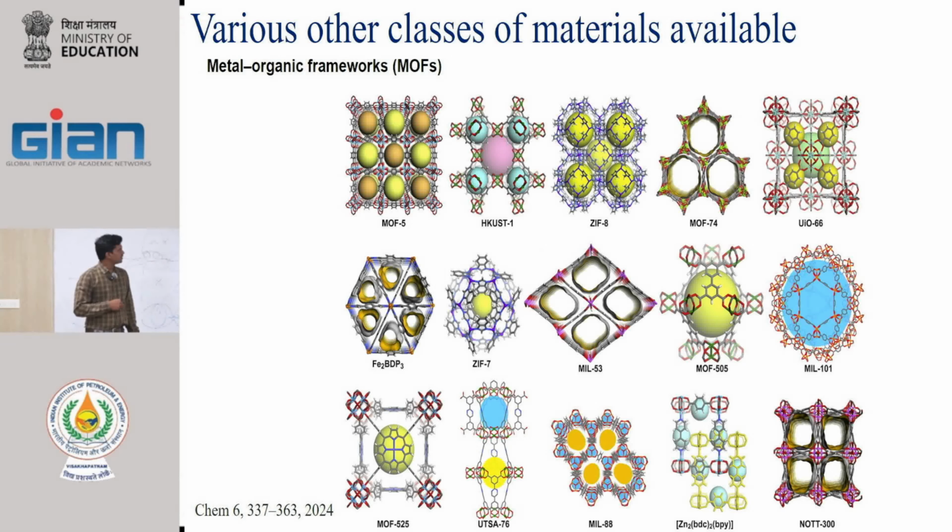So different sizes, different shapes, and these are actually flexible molecules, unlike zeolites. The zeolite pore structure is well defined, most likely a crystal, so the pore sizes are almost the same all the time. But with the metal organic framework, when the gas molecule enters the system, the framework either compresses or expands depending on the interaction between the gas and the MOF material.